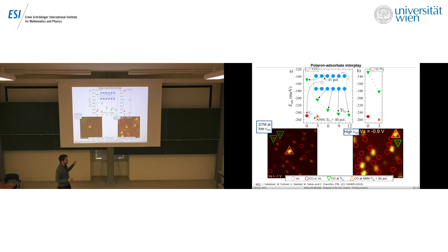And how about spin-orbit coupling? Does spin-orbit coupling play a role? We didn't do it on the surface, but we did some calculations in the bulk, and it didn't change anything. We were looking just at the agreement of the band gap, and adding spin-orbit coupling didn't change the band gap much. And regarding the spin alignment of the bipolaron, this is a spin-up bipolaron. The transition metal sites like to maximize the spin, so they go up, up.